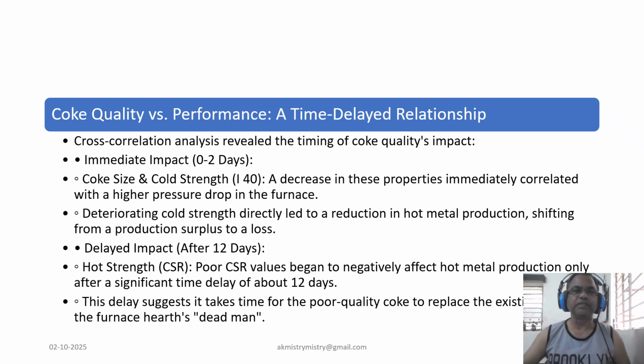So, how quickly did this problem appear? A cross correlation analysis revealed two different timelines. The immediate impact within 0 to 2 days was linked to coke size and cold strength. As the cold strength dropped, the pressure drop in the furnace immediately increased and hot metal production quickly shifted from a surplus to a loss. However, the hot strength CSR had a delayed impact. It took about 12 days for poor CSR values to begin negatively affecting production. This delay is because it takes time for inferior coke to work its way down and replace the existing high quality coke in the furnace dead man. This shows that while cold strength is critical for the immediate stability, hot strength is absolutely essential for the long term health and performance of the furnace.